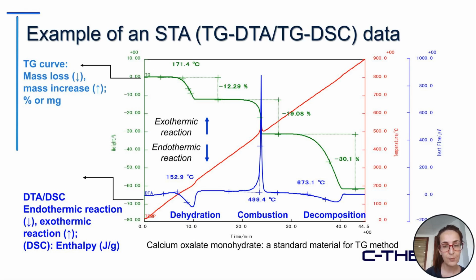Then we have the second mass loss, which is related to the combustion of the calcium oxalate. Since this experiment is done in air, we also have some evolving of carbon monoxide and carbon dioxide. And finally, we have the last mass loss, which is related to the decomposition of the calcium carbonate.